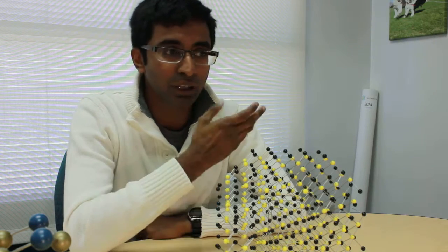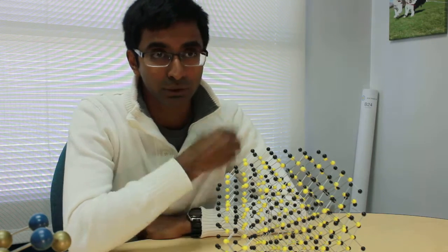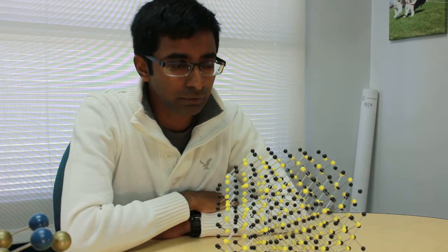The problem there, though, is that when you build something to harness thermal energy that's not from the sun, then you have to know where the spectrum is. So for instance, if you're designing something to use energy off of a car's exhaust or an engine, you probably might want to target 4 micron absorbers and grow stuff that's in 4 microns. Then you do that with antimonide semiconductors. For instance, the propane flame based technologies can span 1.5 to 2.4 microns. I've seen examples of them in that range, where people have a furnace to heat their homes in the winter, and then they can also use the excess energy to then maybe power a light bulb or so.